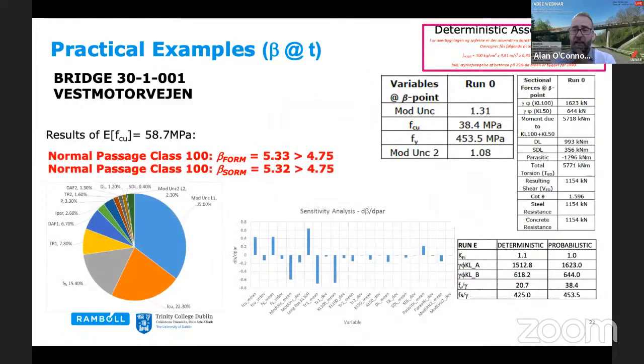And the results of that analysis were that we were able to document that the structure had adequate capacity, in terms of a beta value being above the target level for this structure at the critical limit state. And we were able to not only ascertain those values, but also perform a sensitivity study. If you look at the pie chart, we could see what the importance factors were. If you look at the sensitivity study, shown in the middle of the slide, we can see the influence of the modeling of the parameters on the computed beta value.